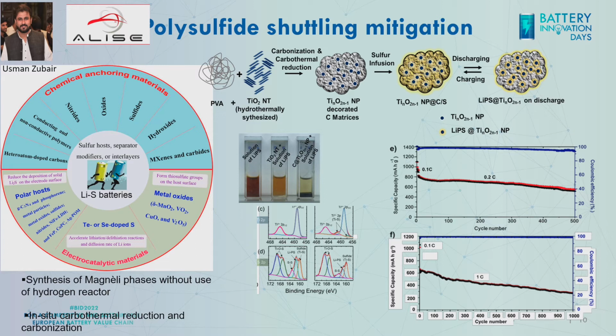And on the other side are electrocatalytic materials that can accelerate the lithiation reactions and also the diffusion of lithium ion in the more viscous electrolyte. Here I'm showing you a couple of results that we achieved in our group. This is one of the results of the ALISE project, performed by Usman Zubair, who was one of our PhD students and is now a professor at a university in Pakistan. He worked on titania. Titania is very cheap and easy to get. He prepared some materials hydrothermally with titanium nanotubes that, with carbothermal reduction, are transformed into spherical particles.